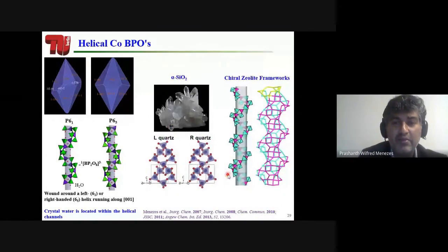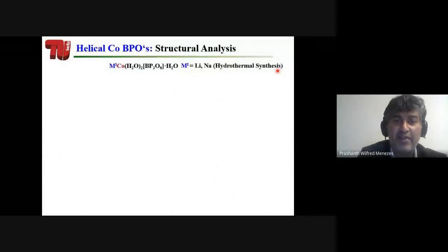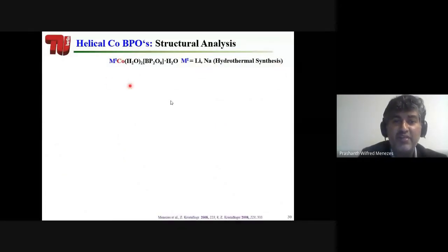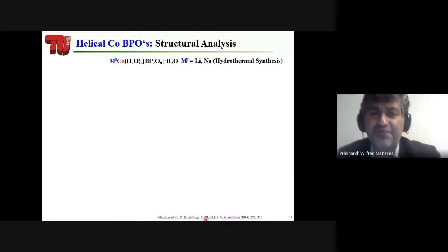And interestingly, one of the most interesting aspects is that you could see the structural similarity of helices with alpha quartz. This is the most common compound which you see in sand, and it's also very close to the chiral zeolite frameworks. These materials are very well known for gas adsorption. This is somehow zeolite modified frameworks. And okay, so now we know that we could produce such cobalt borophosphate.